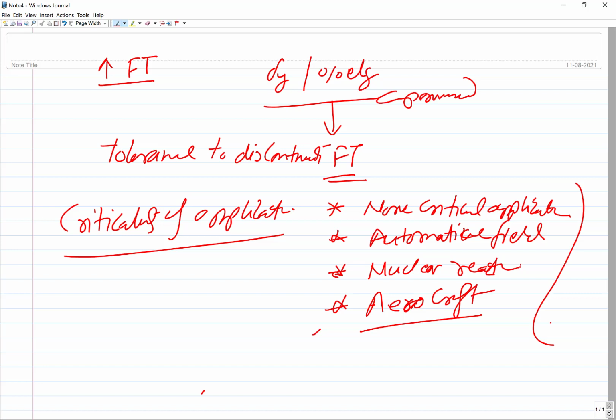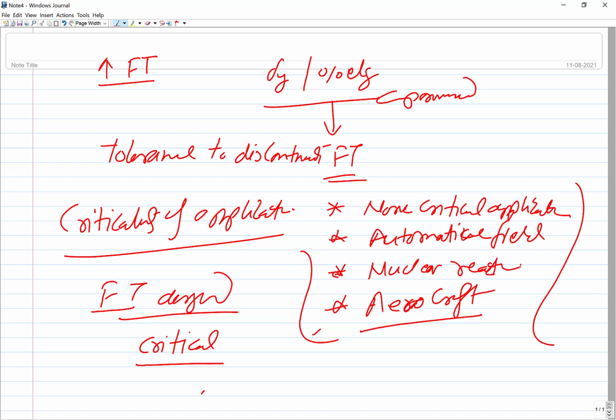So the damage tolerance, or the tolerance to discontinuities, should also be linked with the criticality of the application. That is why the fracture toughness based approach for designing a weld joint you may not use for non-critical applications, but certainly it must be used for all those cases where there is a threat to life and a threat to property at a greater scale. So for critical applications, you must assess the tolerance to damage, and damage tolerance is compromised somewhat less in solid state joining than in fusion joining. So the damage tolerance is in general good for solid state joints. I think I have talked a lot about damage tolerance.